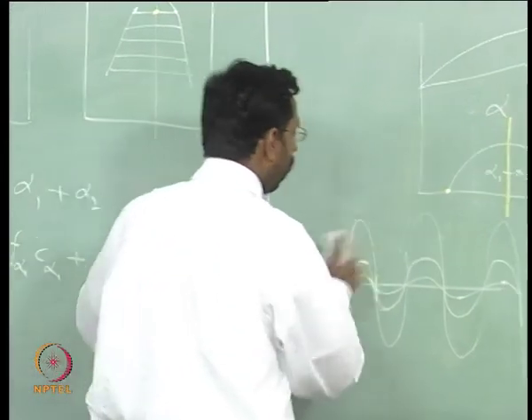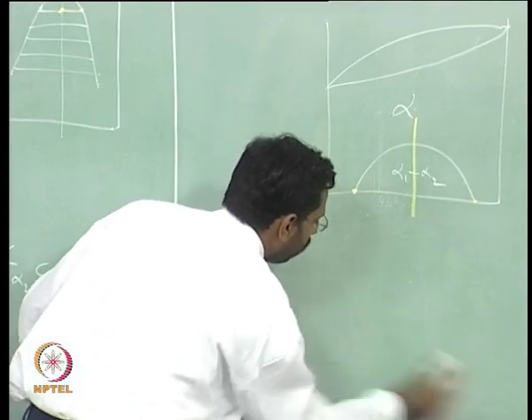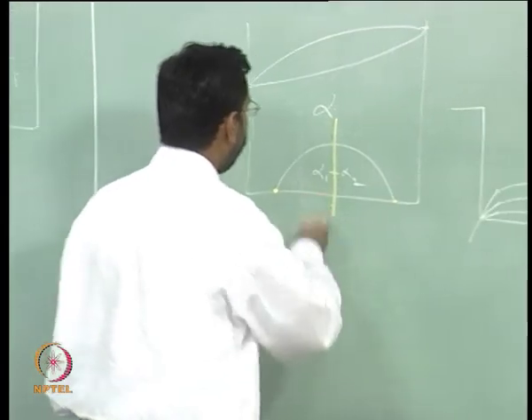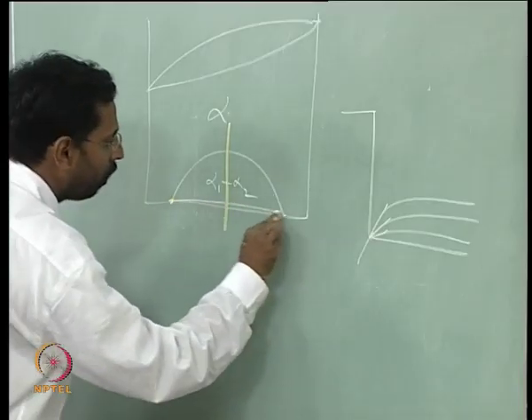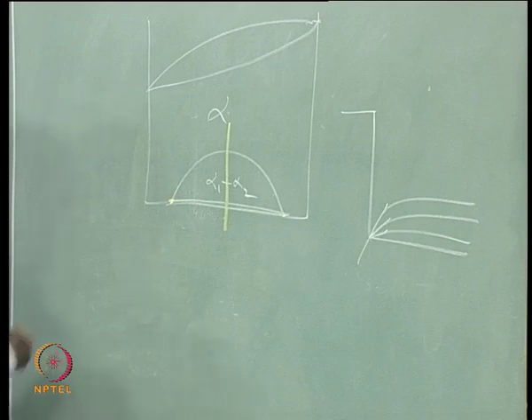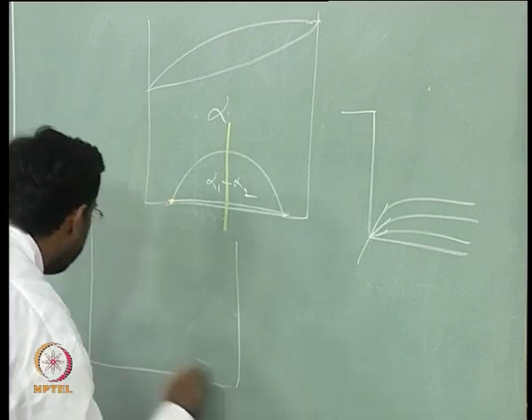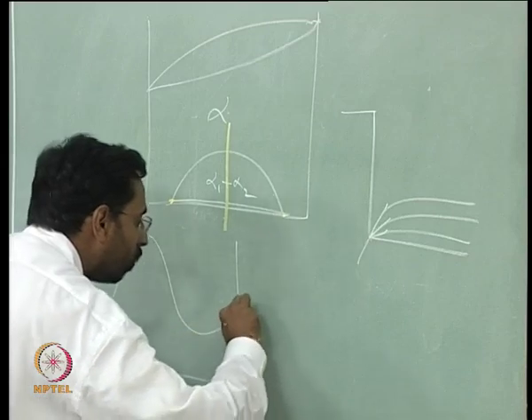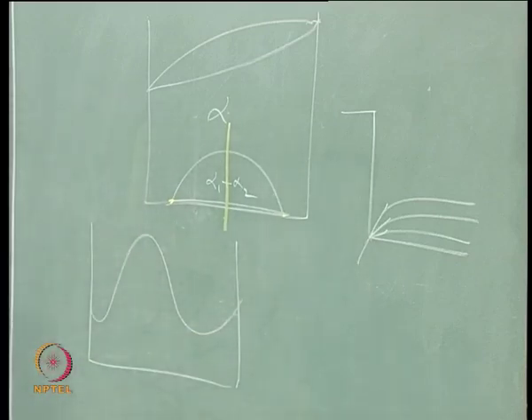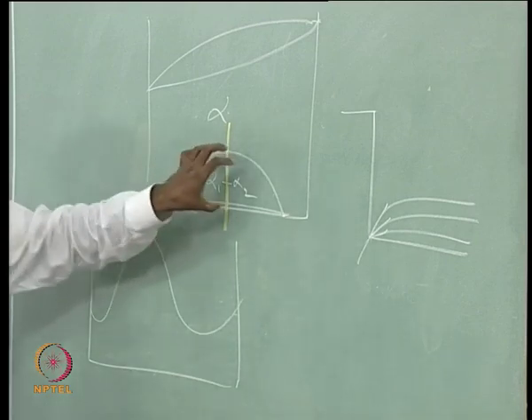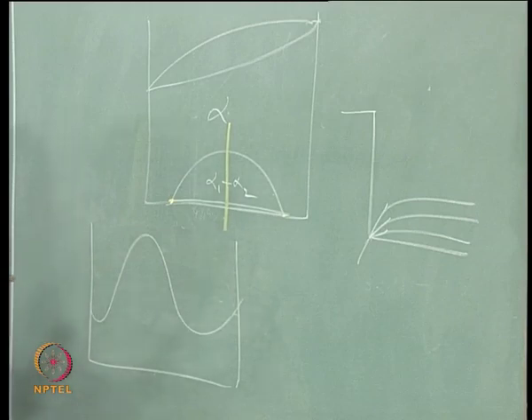And how do I understand this from the free energy point of view? Let us now try to draw the free energy curve at this temperature for this. If I draw the free energy curve, it actually looks like this. Am I right? Because when do you get a miscibility gap? When the delta H is positive. Whenever the delta H is positive and that is higher than the T delta S mixing term, then you will see the free energy curve will have this kind of a shape.